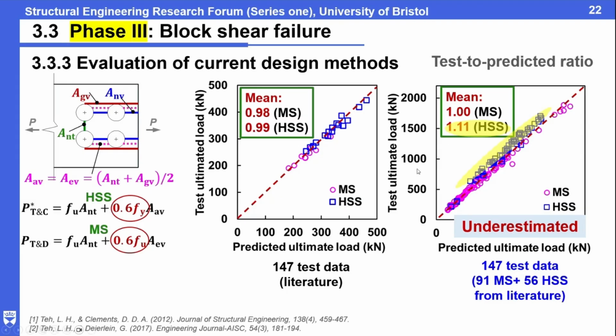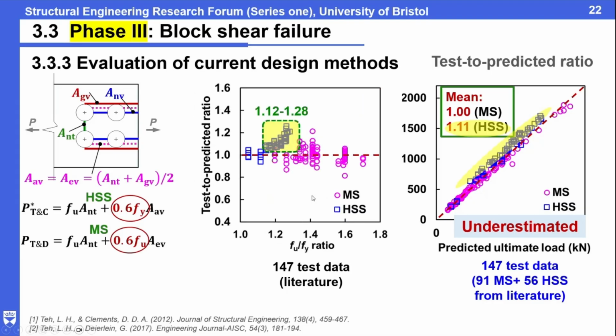I compared many parameters to the ratio until I found that when I plot the test to predict ratio versus the Fu over Fy ratio, the strength ratio, we found that these dots above 1 are exactly the high strength steel. And when we look further at the strength ratio, it ranges from 1.12 to 1.28. It means if the strength ratio is located in this range, they actually have some strain hardening already, but we ignored it. So that's why we have the underestimated results.